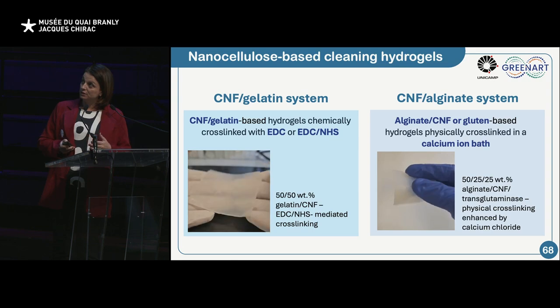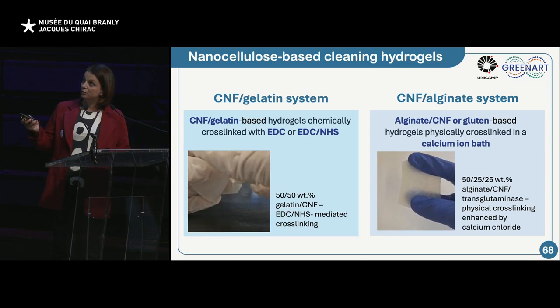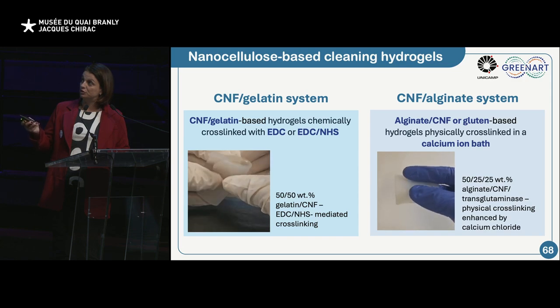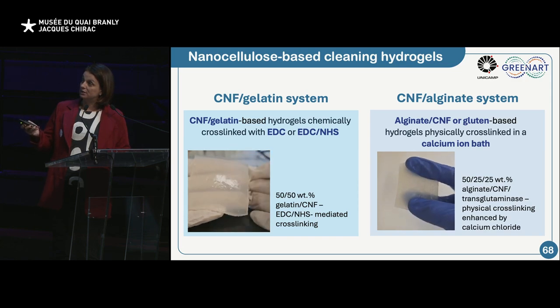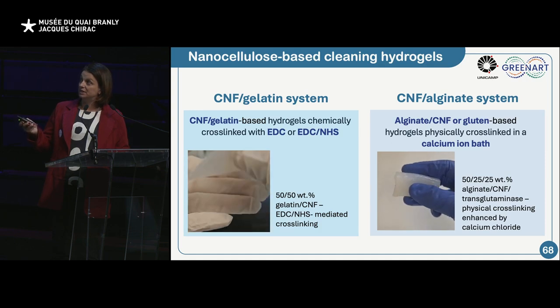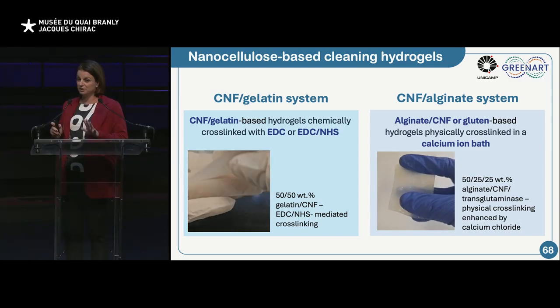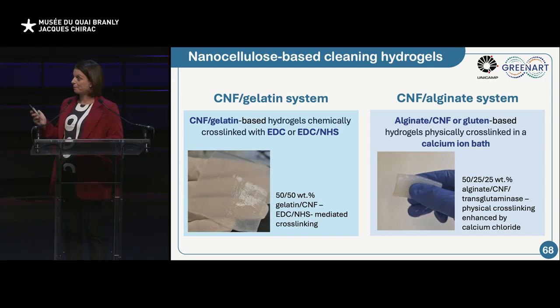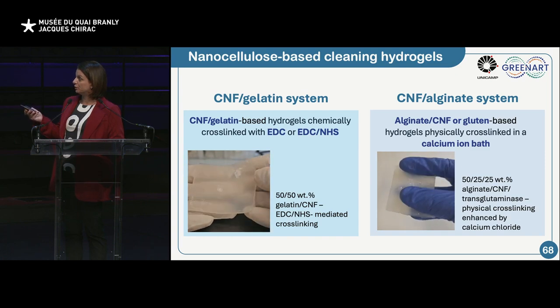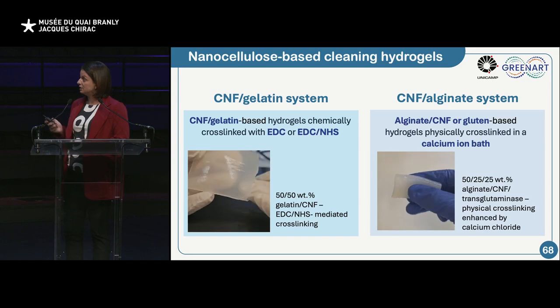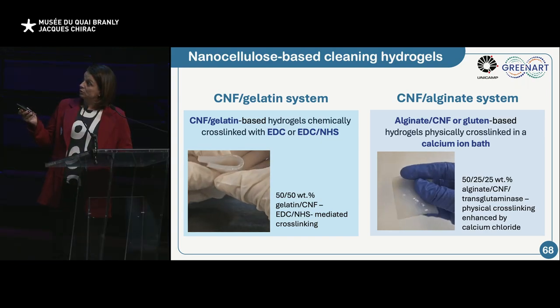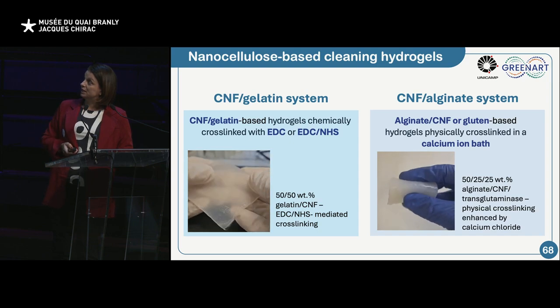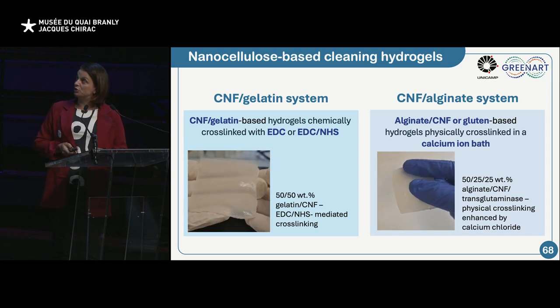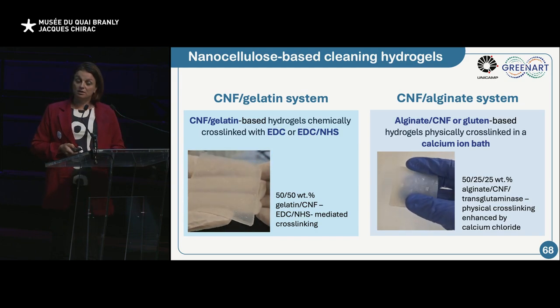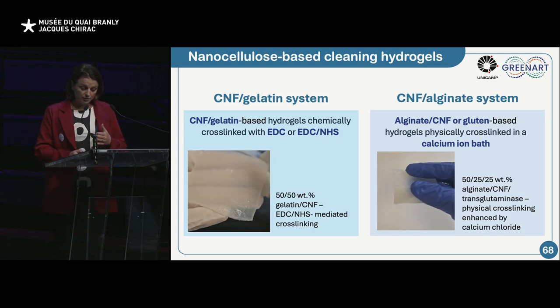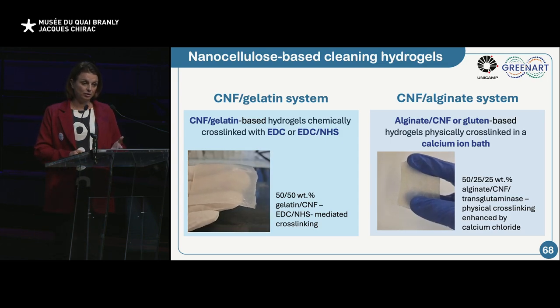We have mainly two systems that we are working with in the laboratory. So CNF, cellulose nanofibrils, with gelatin. They are chemically cross-linked using EDC or EDC NHS. I will not stress very much this chemistry, but it's something very used for compounds like gelatin. And we also work with alginate CNF or with gluten-based hydrogels, which are physically cross-linked using calcium bath. So both chemical and physical cross-links work very well for gels.